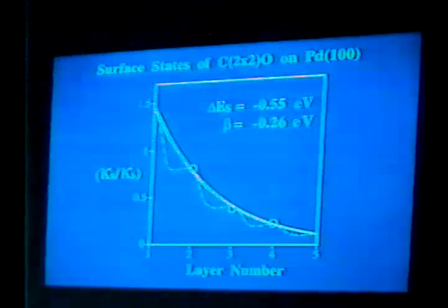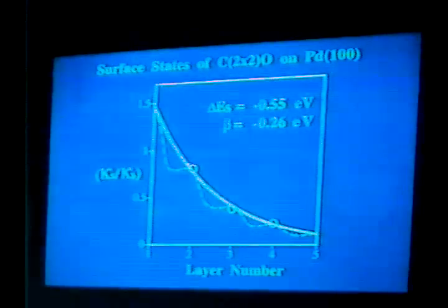If one takes the ratio of these two for three subsurface layers, second, third, and fourth, these are experimental points where the intensity of the surface peak has been measured when these emissions were identified as coming from the second, third, and fourth layer, and measured in relation to the reference, which was the bulk palladium emission. One sees that this core level measured surface state extends into several layers and exponentially decays in it.